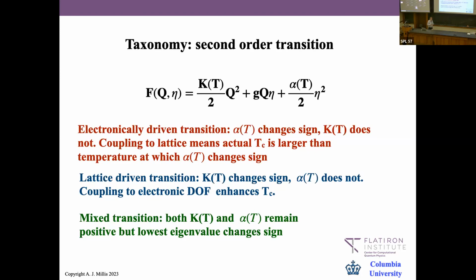Okay, so once you see this, you can make an obvious taxonomy. I will say this is an electronically driven transition if this guy changes sign, and then the cross coupling will just move my transition temperature around a little bit. I will say I have a lattice-driven transition if this guy changes sign, and again the cross-coupling will move things around a little bit. And I will have a mixed transition if neither one changes sign, but the cross-coupling is strong enough that the lowest eigenvalue can change sign. So that's an elementary taxonomy of electronic, lattice, or mixed transition.